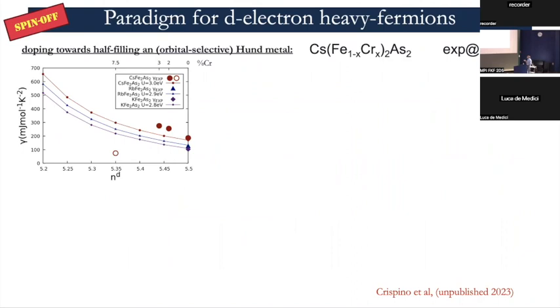And indeed, what is very nice is that we took the most correlated of all these 5.5 iron-based superconductors, which is cesium iron 2 arsenide. We put some chromium, and they got the value of the Sommerfeld coefficient to hit the record for iron-based superconductors, and one of the highest values that you will ever find in the electron system. So we think that this, we indicated this road, and this goes quite well also with theory.